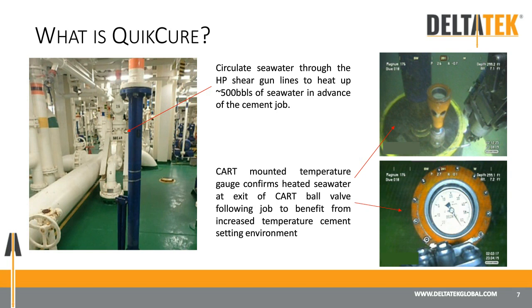But further evidence that there's no detrimental effect to the cement is the fact that on every quick cure job that DeltaTek has executed in the field, the recovery of the core cure sample has categorically proven that the cement at the highest exposure of temperature is of the highest quality, with all the compressive strength that one would expect of it, without any detrimental effect. So there's great confidence that there is no detrimental effect on the cement.